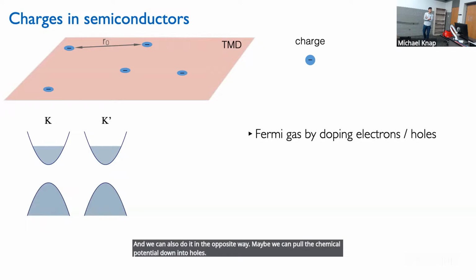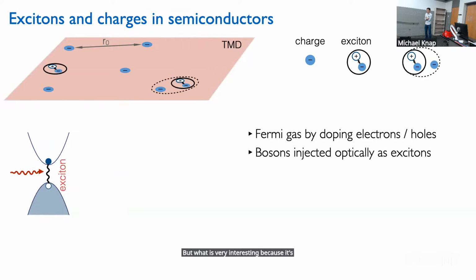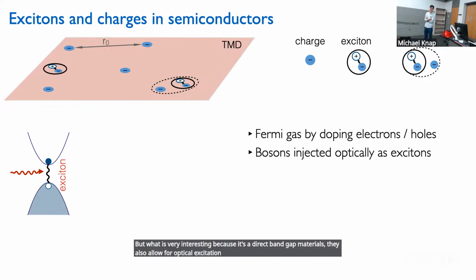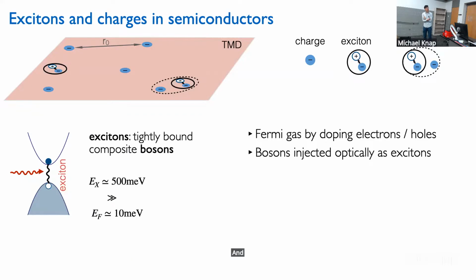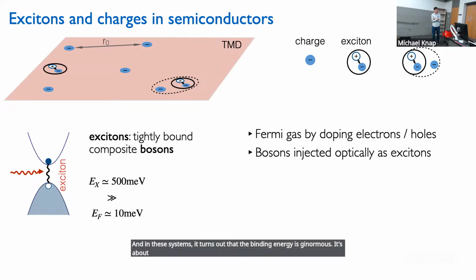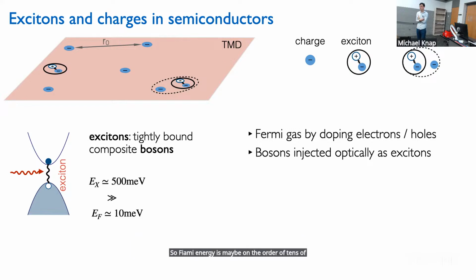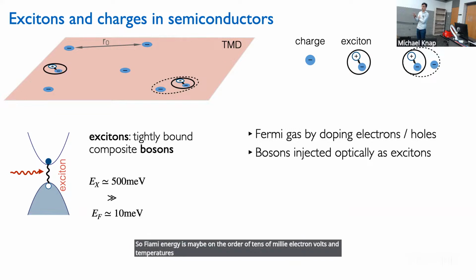But what is very interesting, because these are direct band gap materials, they also allow for optical excitation and the formation of excitons. So these are bound states of electrons and holes. And in these systems, it turns out that the binding energy is ginormous. It's about half of an electron volt, which is much larger than all the other scales which we typically consider in this system. So Fermi energy is maybe on the order of tens of milli-electron volts, and temperatures, of course, are much lower, right? Because room temperature, as you know, is 25 milli-electron volts.